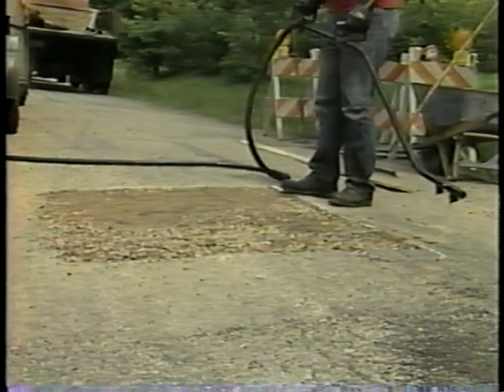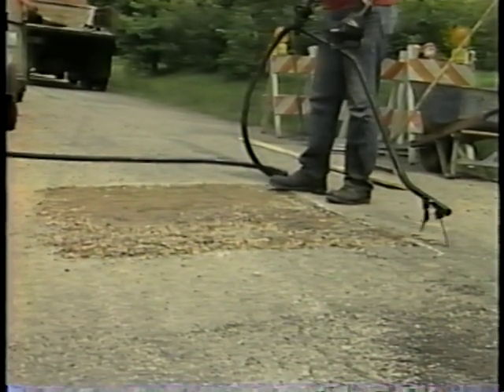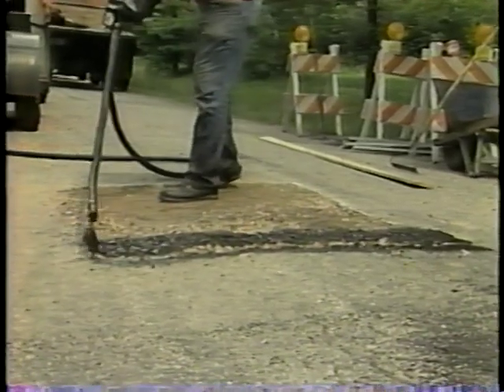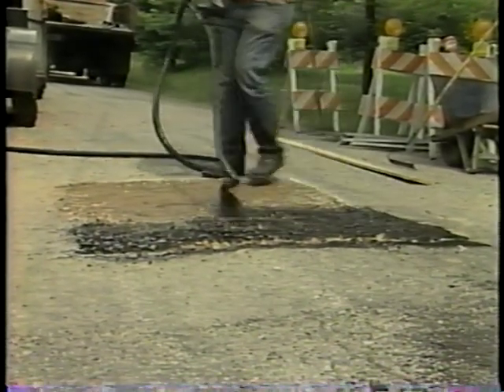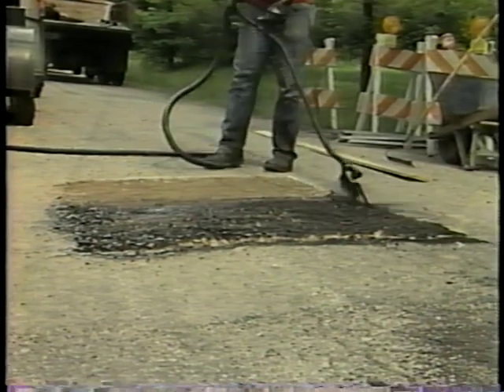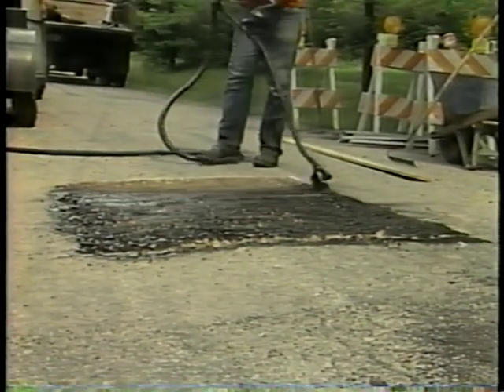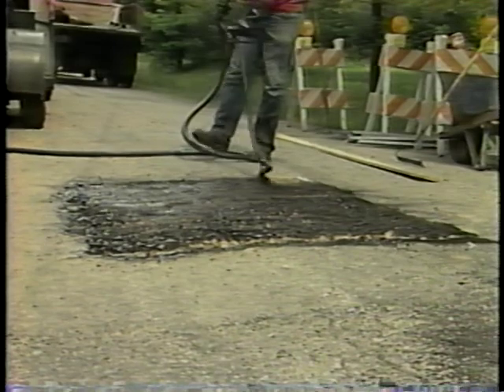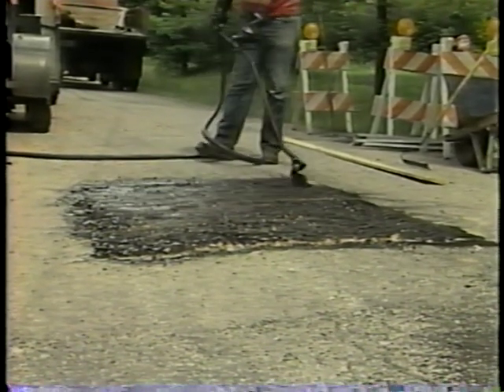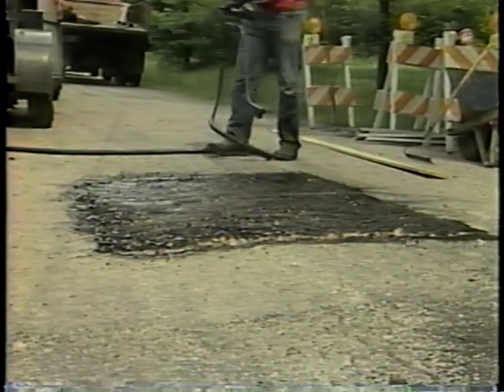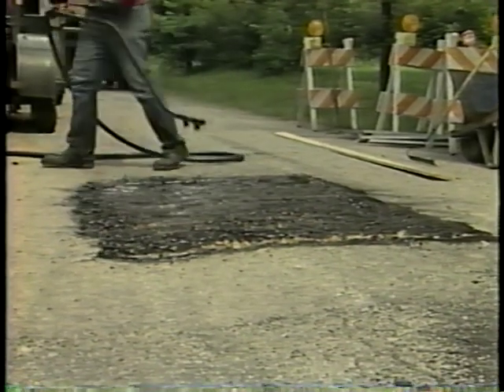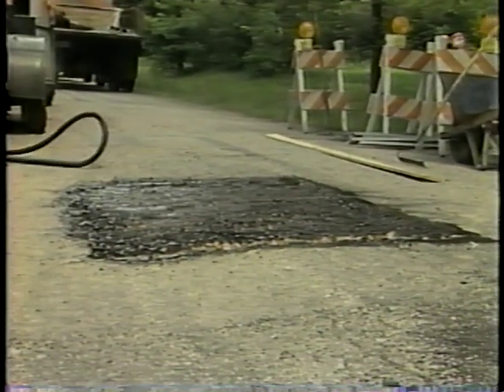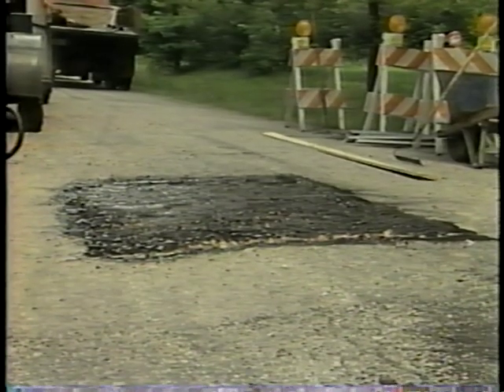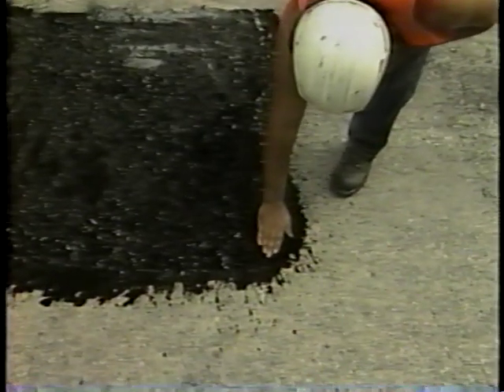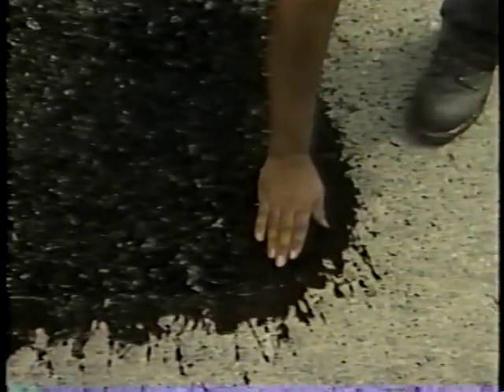Step 6. Seal the surface with liquid asphalt and cover aggregate. To begin this process, apply the liquid asphalt using an asphalt sprayer or an asphalt pouring pot if you do not have an asphalt sprayer. The surface must be clean and dry. Make the application thick enough to soak into the patch and form a light coating over it. Overlap the asphalt onto the existing pavement 8 centimeters, or the width of your hand.